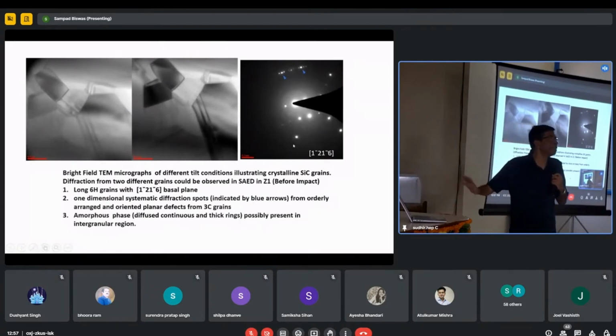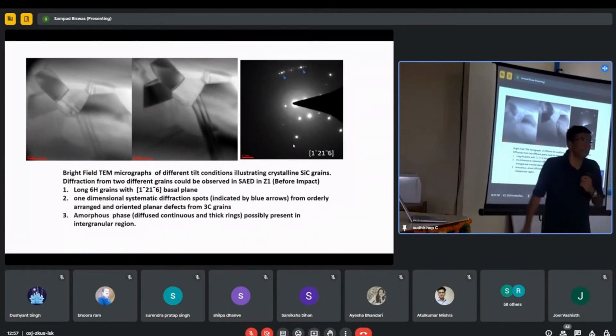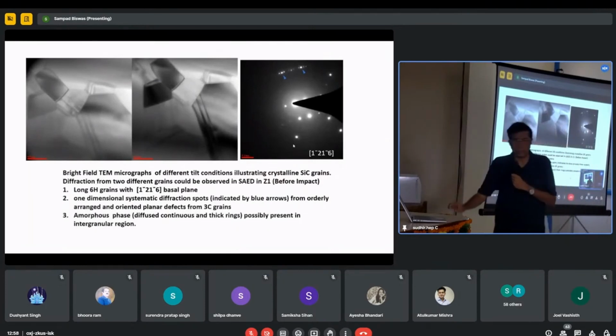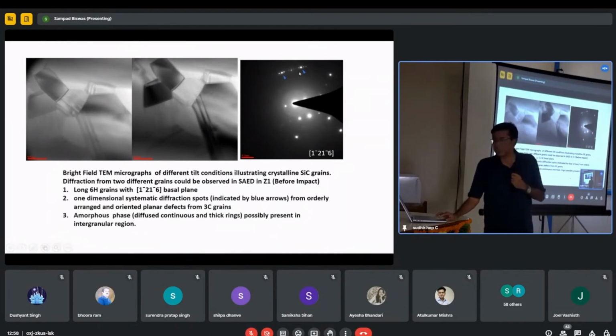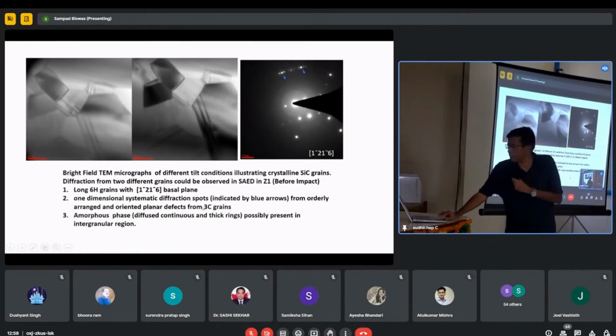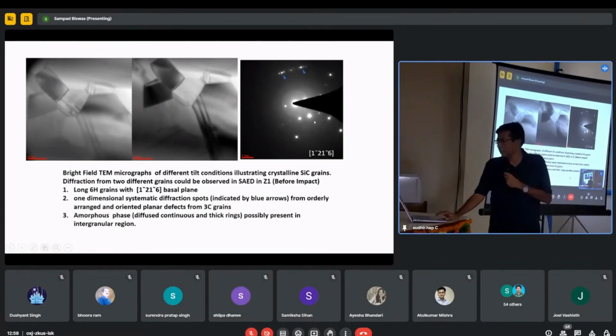This SAED pattern is a double diffraction pattern from which you can analyze that two different crystals could be identified. One is the 6H variety, the other one is the 3C variety, and this is a typical spot pattern of any stacking fault. Now, another important area we have found is the amorphous phase; diffuse rings we can find from this TEM. This amorphous phase is a very important area, and we presume that it was present during the sintering process, because other materials didn't have this amorphous phase.